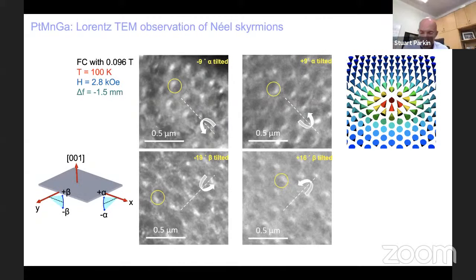And these we can see almost to room temperature. So the conclusion is these chiral spin structures are multiple. And even in one structure, you can stabilize metastable states which have entirely distinct structures. But in all cases, the chiral structure and the chirality is intimately linked to the symmetry of the underlying Dzyaloshinskii-Moriya exchange.